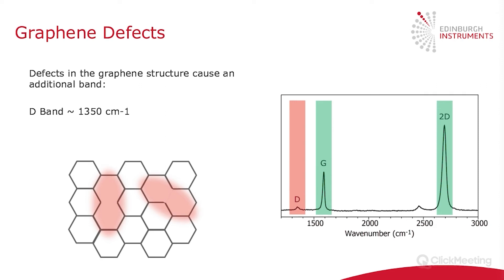Controlling these defects is very important for electronic applications, as they change the electronic properties of the graphene. Examples of defects include dislocations in the lattice, or simply where the lattice ends. When these defects are present, an additional Raman band becomes active — the D band at 1350 wavenumbers. So Raman microscopy can be used to image the location and density of defects within your sample.